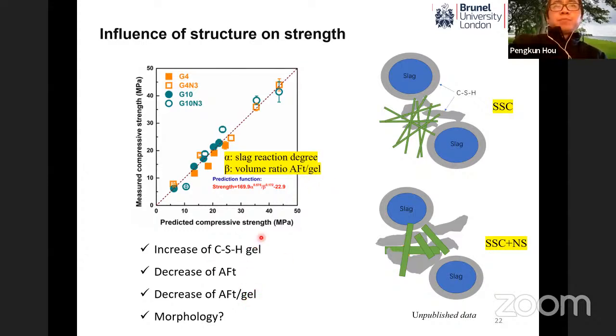How will these features affect the mechanical property? So we did a regression study showing that the reaction degree of slag, that is the CSH gel amount, and the volume ratio of ettringite to gel are closely related to the strengths. So this can well explain why the nanosilica improved the strength and how the structure was modified, and how the strength can be improved by nanosilica.